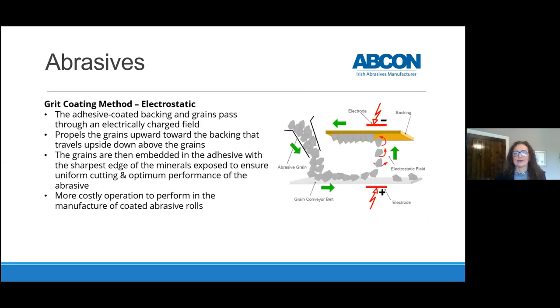So the second method is the electrostatic method. This is where the adhesive coated backing will pass above the grain, and they're passed through an electrically charged field. So this field propels the grain upwards onto the material, and the grains are embedded in the adhesive with the sharpest edge of the mineral exposed. And in the end product, this will ensure that you achieve uniform cutting and optimum performance of the abrasive. So this operation, obviously, as you can imagine, is more costly to perform.